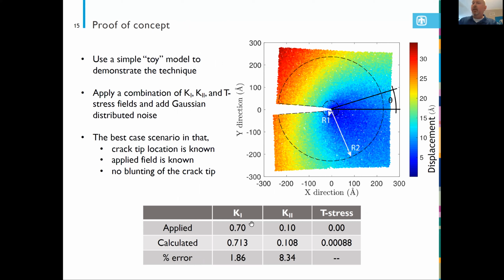And so by looking at the differences between what we know we applied and what we calculated, we can back out the error of the method. And I note that our toy model is the most ideal case in this situation. I know exactly where the crack tip is. I don't have any sort of blunting that may be consistent with the displacements that we will later see in atomistic modeling. And ultimately, I'm going to be modeling the displacement fields in an annulus that surrounds the crack tip region.